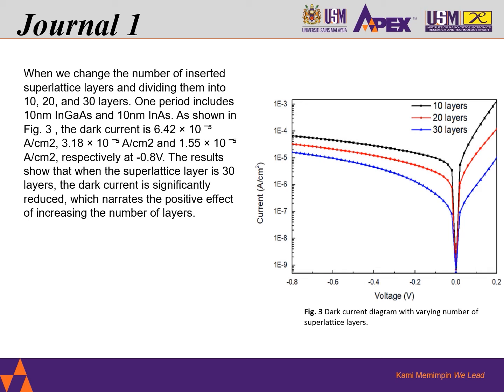The dark current is 6.42 times 10 to the minus 5, 3.18 times 10 to the minus 5, and finally 1.55 times 10 to the minus 5 respectively at minus 0.8 voltage. The results show that when the superlattice layer is 30 layers, the dark current is significantly reduced, which shows the positive effect of increasing the number of layers.